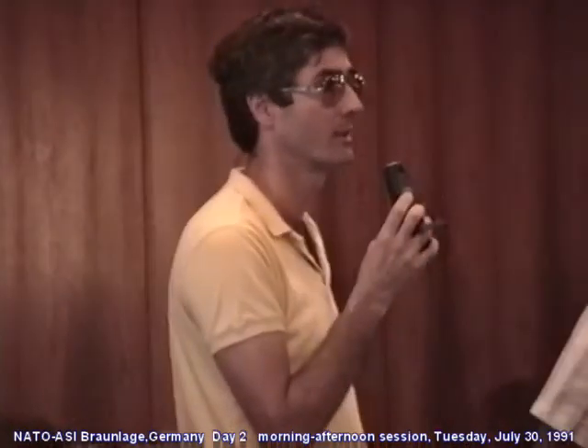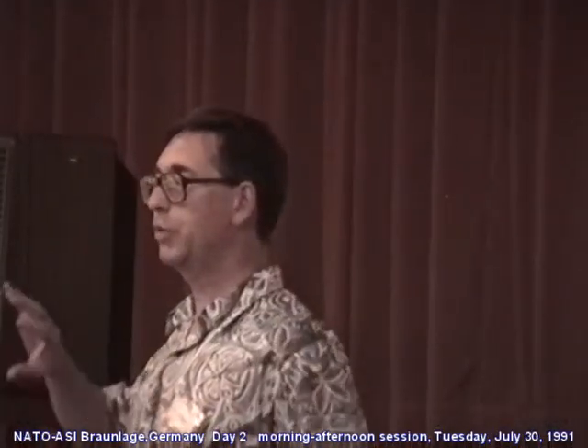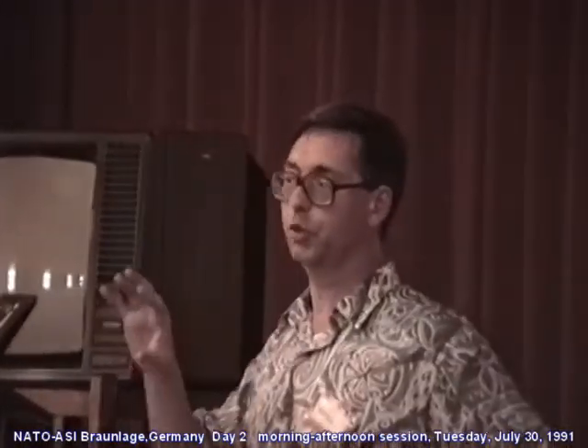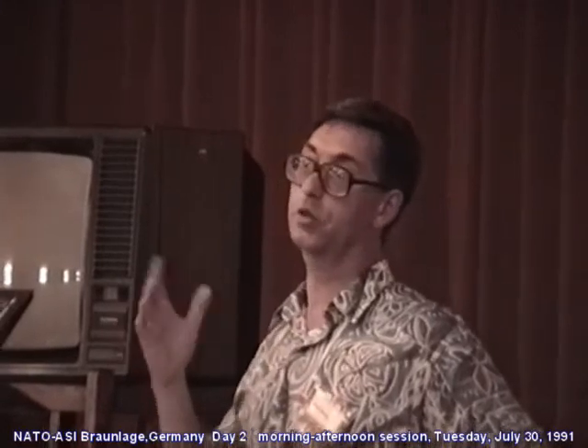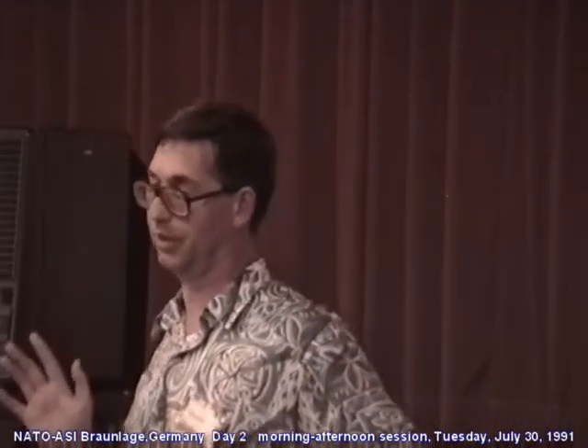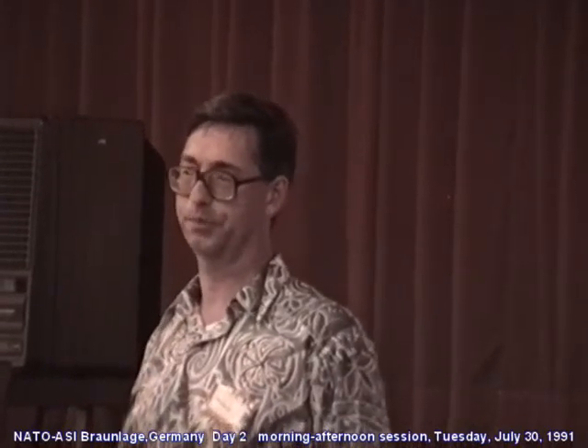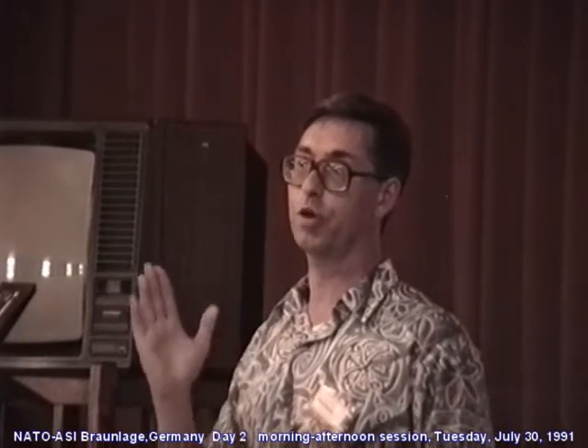That's correct. I was wondering what the coupling between different modes was, because if you have coupling between the modes, you would have a synchronization of frequencies, I believe. Yes. This is the reason why I said it was an exploratory experiment, because when we used the motor, the signal was found noisy at the beginning, and the signal was filtered. It was not a good idea. In a second study, we put the roller on a spring and measured the deflection with the spring, but we had coupled oscillation at this time. I have not insisted, because it is more difficult to understand. So if anybody tries such an experiment, it is necessary to have a very stiff system to avoid coupling oscillation.